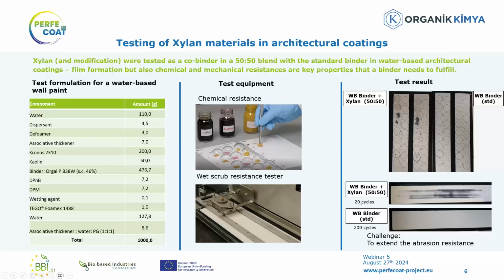And this also on the wet scrub test that you can see at the bottom right, after 20 cycles, we start to see the substrate show, indicating that the abrasion resistance is a bit on the weak side. We would expect to really meet the standard of the industry to reach 200 cycles. That's what is accepted in terms of quality.